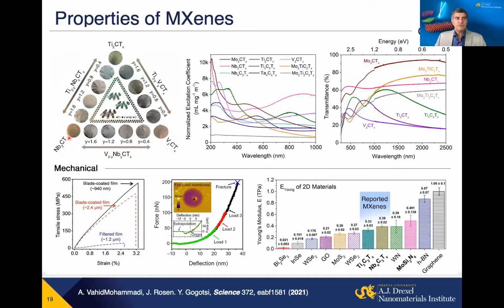And of course, you can do this tuning of colors, but it means positions of surface plasmons and other properties, even more finely by forming solid solution, mixing different amounts of transition metal, and you will smoothly change positions of plasmon resonance peaks that you can see here. Also, you will see that these plasmon resonance absorption peaks, those surface plasmons, cover a very wide range of wavelengths. There are electronic transitions in the UV range, and then we go from UV to infrared. And they have very high mechanical properties as well, not as high as single layer of materials produced by CVD, because they still have some defects, but they are higher than solution processed materials.